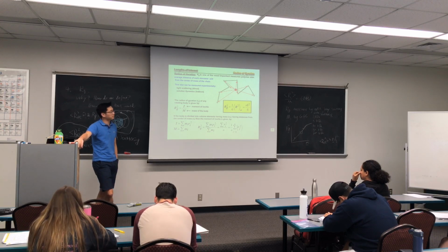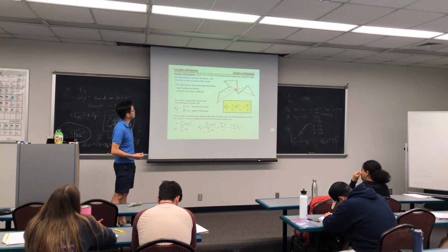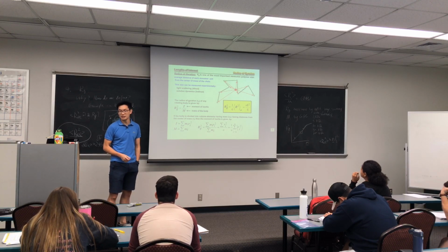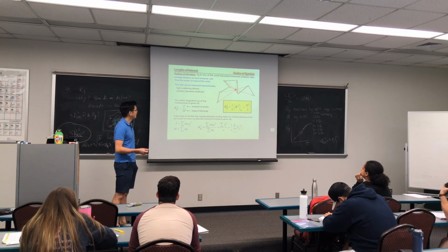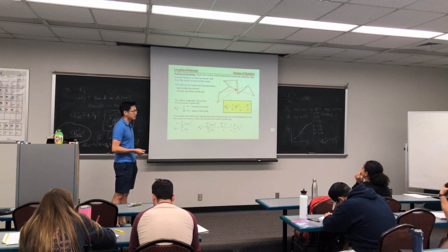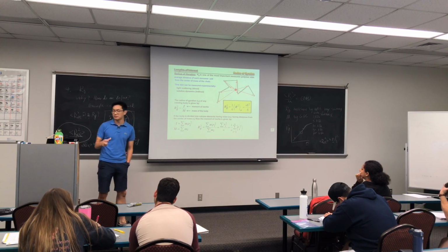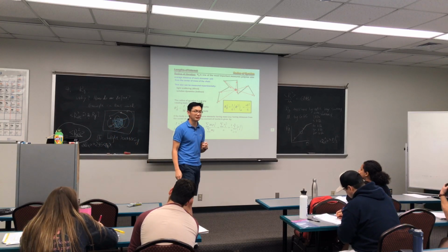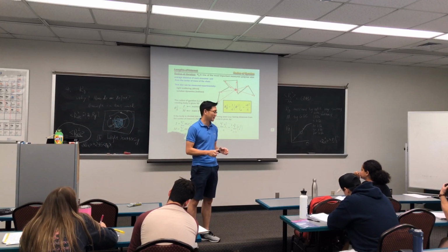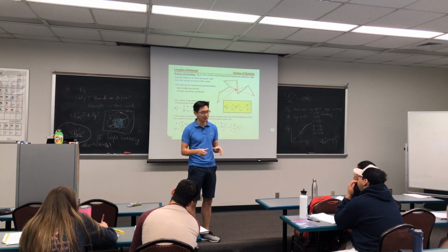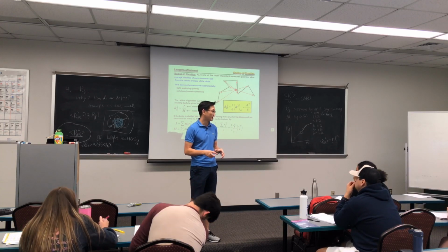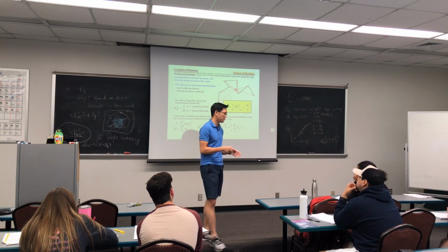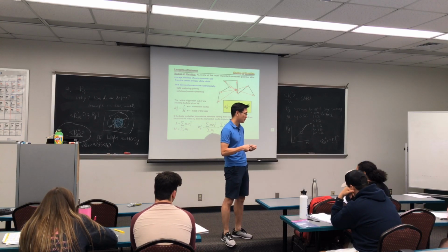So this is, again, probably the most important measurement of polymer size you would encounter. And if you are interested in measuring your polymer size in solution, this is the best method to go. In this methodology, what you would do is dissolve the polymer at a relatively dilute concentration, something like 1 milligram per ml or a few milligrams per ml.